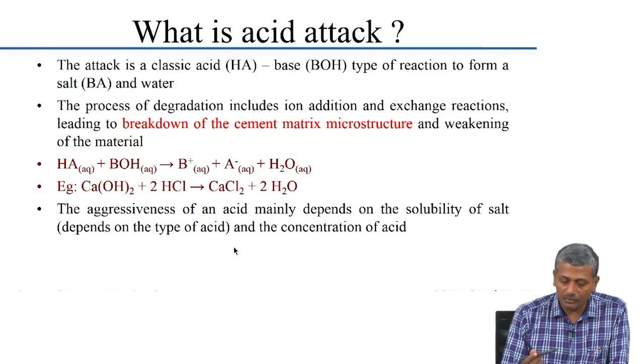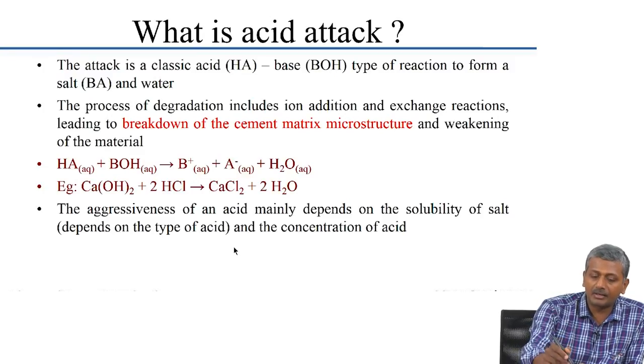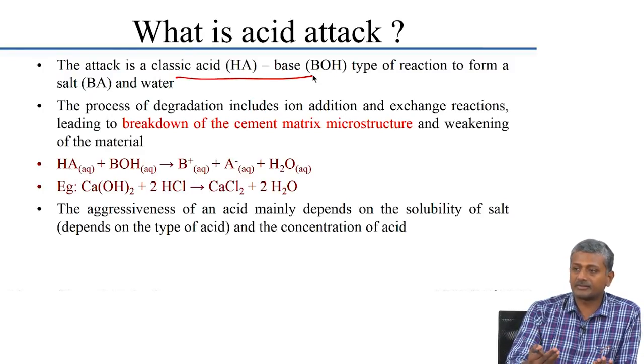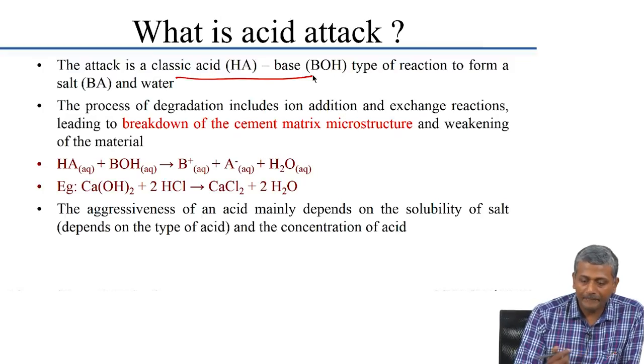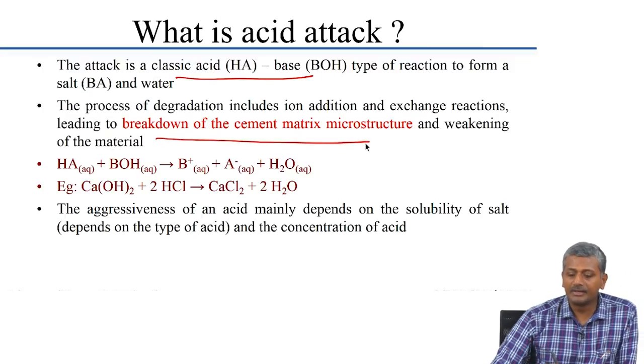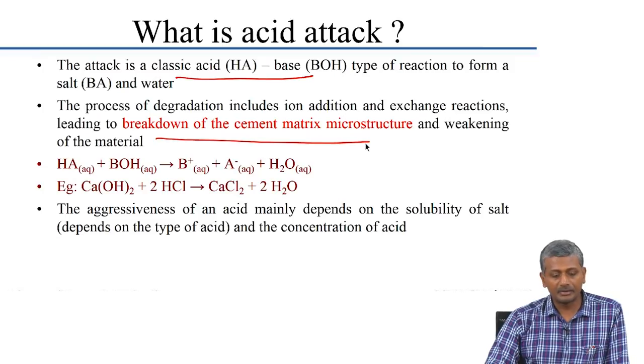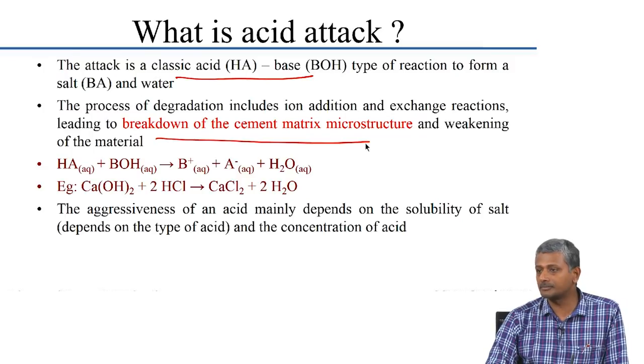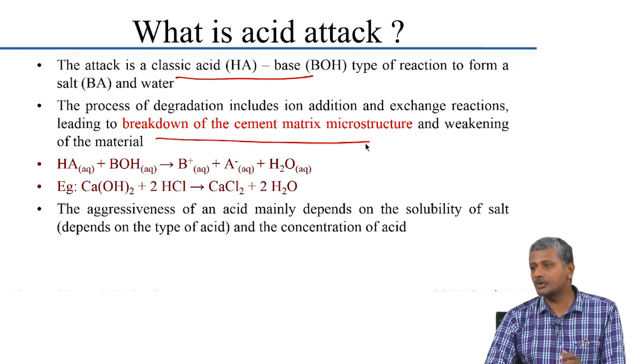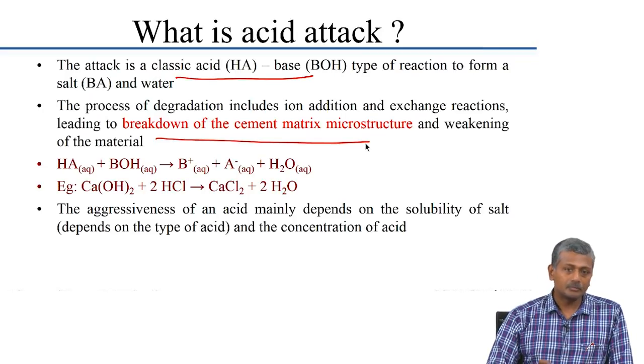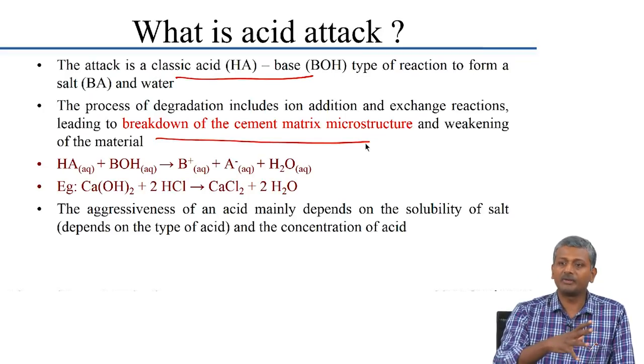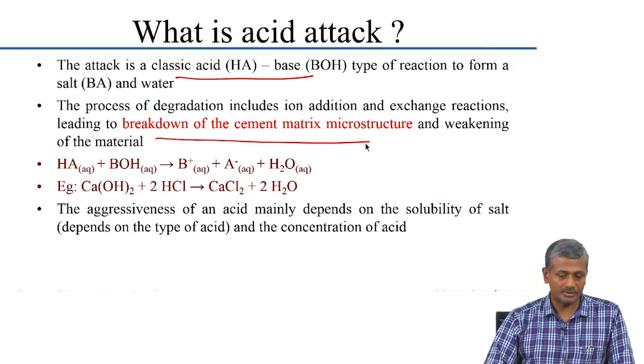Acid attack is a classic acid-base reaction: acid from the external environment reacts with calcium hydroxide and other basic substances in the cement hydration products, leading to breakdown of the cement matrix microstructure by formation of salts. Some salts are soluble — leading to increase in porosity; some are insoluble — leading to deposition and possibly expansion. There is a zone that forms because of interaction between the outward-moving calcium-bearing species, silicon and aluminium and hydroxyl ions, and the inward-moving acid anions and protons.